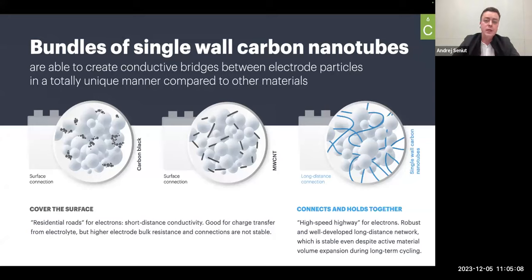At the same time, single-wall carbon nanotubes create long-distance connections and bonds between the particles of active material. And these bonds act like some sort of high-speed highways between active material particles, which are highly conductive and highly strong. And thus, these connections allow conducting high currents and are stable even, for example, when there is a severe volume expansion and contraction of your battery active material.